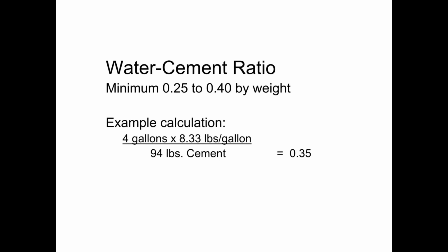Now in your book it mentions that we need a minimum of 4 ounces of water to fully hydrate a pound of cement. And so what that means is that we need a minimum water cement ratio of 0.25. If we have a water cement ratio of less than 0.25, then we don't have enough moisture available to interact with the cement to fully hydrate that cement.